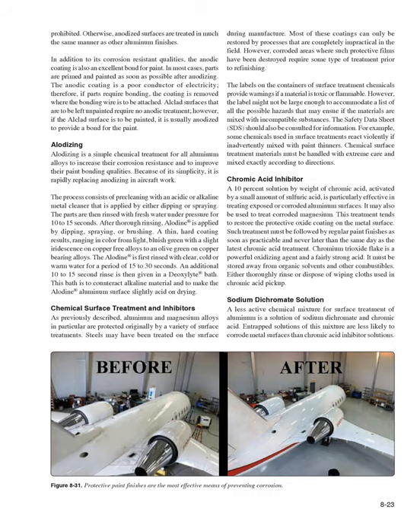Alodizing is a simple chemical treatment for all aluminum alloys to increase their corrosion resistance and to improve their paint bonding qualities. Because of its simplicity, it is rapidly replacing anodizing in aircraft work. The process consists of pre-cleaning with an acidic or alkaline metal cleaner that is applied by either dipping or spraying. The parts are then rinsed with fresh water under pressure for 10 to 15 seconds. After thorough rinsing, Alodine is applied by dipping, spraying, or brushing.